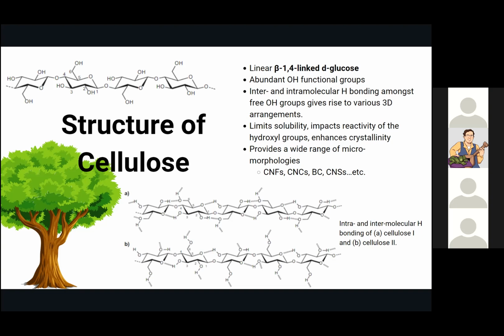Intermolecular hydrogen bonding occurs between C3 hydroxyl and C6 hydroxyl primarily, causing the biopolymer to layer. I did mess up my script, but I believe it's just lower crystallinity than cellulose 2, where intermolecular bonding occurs between C2 hydroxyl groups and C6 hydroxyl groups primarily. So that makes cellulose 2 more densely packed through stronger interconnections and therefore more crystalline.